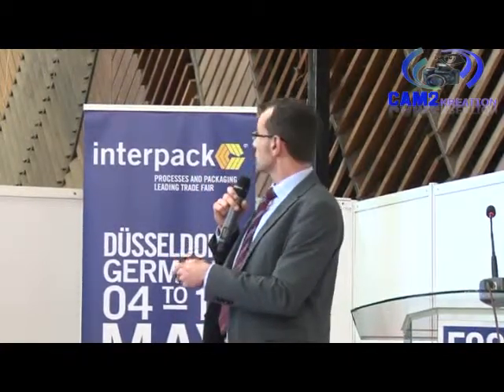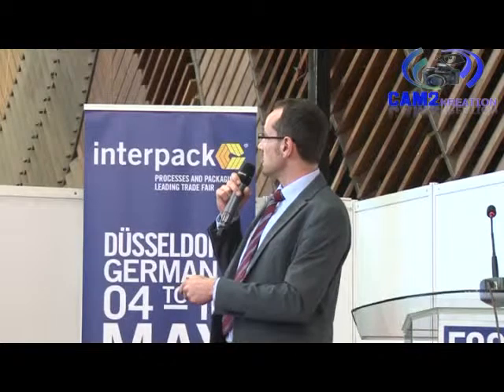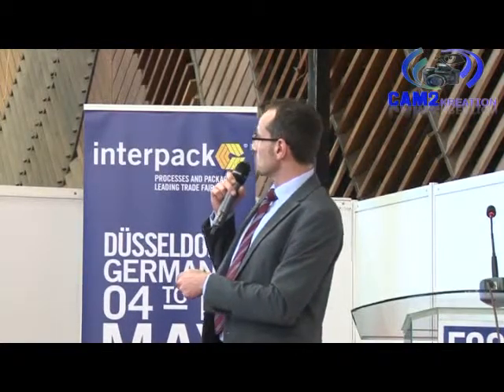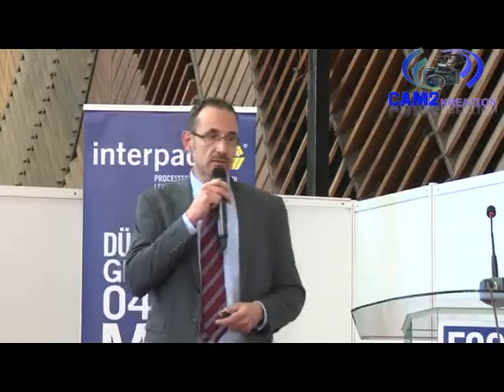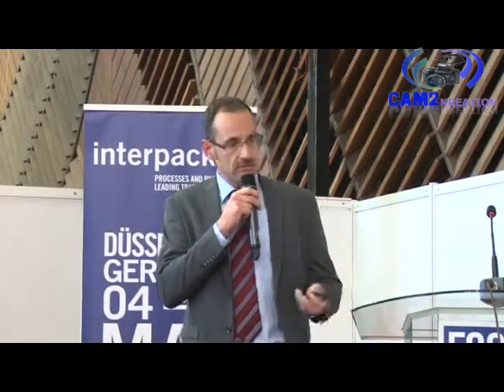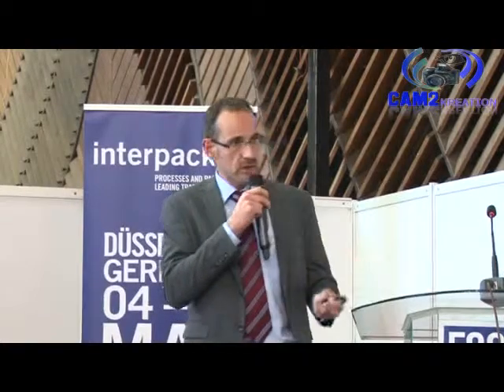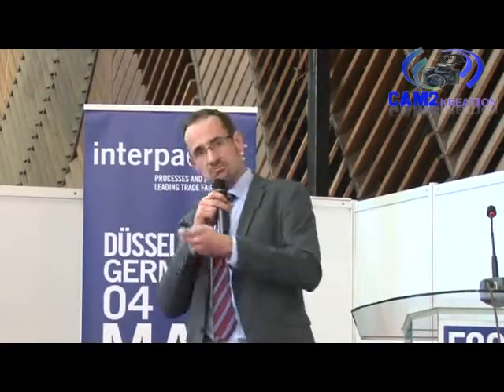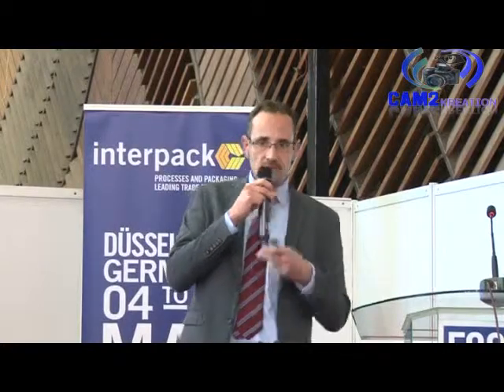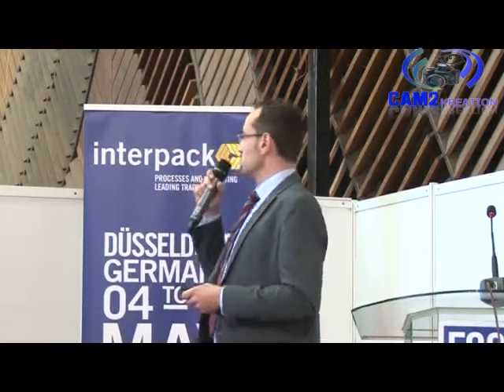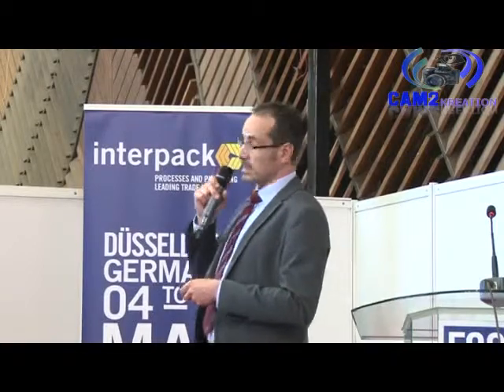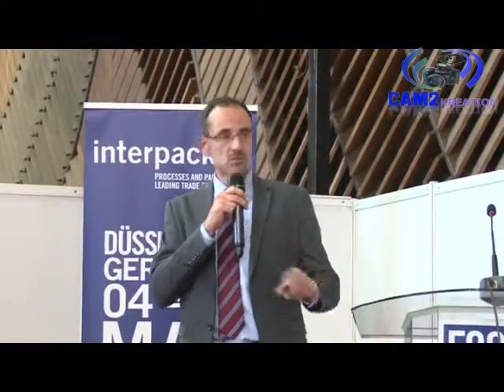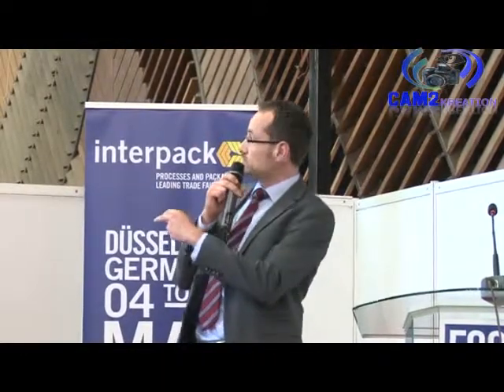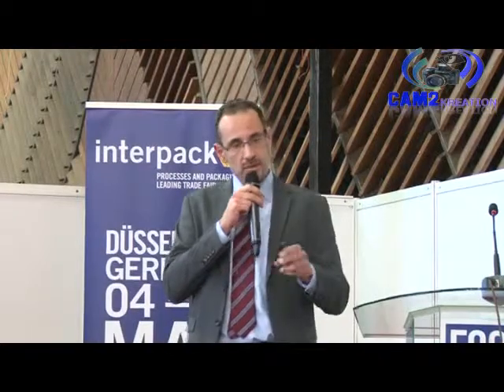The next process is blown film. Also here, almost the same. It can be used from one layer up to 11 layers. This technology is available. In Kenya, I found that most of the companies are running monolayer or 3-layer lines. For nylon we need more or less 5-layer lines, so we also hope that we can do something here. The blown films can also be used directly as co-extruded film: you make your co-extruded film, you make a pouch, and the package is ready, or you use this film for lamination, to laminate against polyester, to laminate against BOPP.